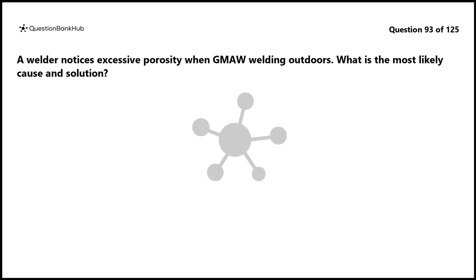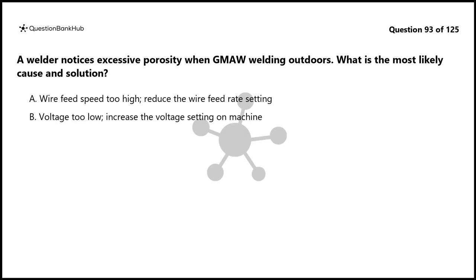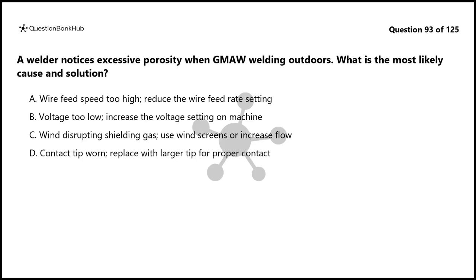Question 93. A welder notices excessive porosity when GMAW welding outdoors. What is the most likely cause and solution? A. Wire feed speed too high, reduce the wire feed rate setting. B. Voltage too low, increase the voltage setting on machine. C. Wind disrupting shielding gas, use wind screens or increase flow. D. Contact tip worn, replace with larger tip for proper contact.